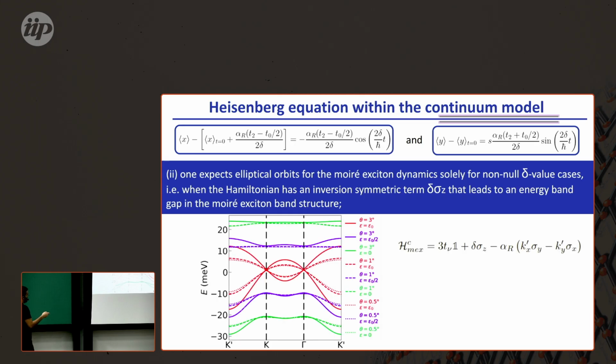Moreover, I have to say that the nice thing about this work is that I realized that any kind of material whose Hamiltonian can be written like an anisotropic Dirac-like Hamiltonian with certain broken inversion symmetry will, due to that, present those cyclotron-like orbits.